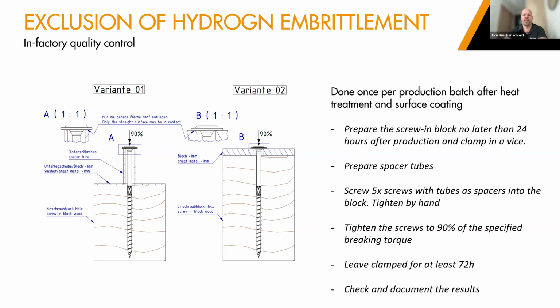Also, part of our QC is that the screws have to fulfill a minimum bending angle. So even having a hardness over 390, we maintain the ductility by checking the bending angle, which is not part of the ETA certification. It's internal QC that we have different bending angles the screw needs to sustain based on its diameter and fully threaded or partially threaded layout. So we really check all the screws frequently, exceeding the hardness of 390, that they are free of embrittlement when they leave production. However, there are factors on site that might be the issue, like heat, saline water, wet timber.